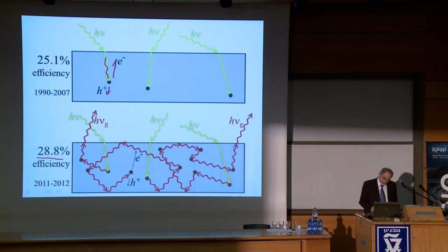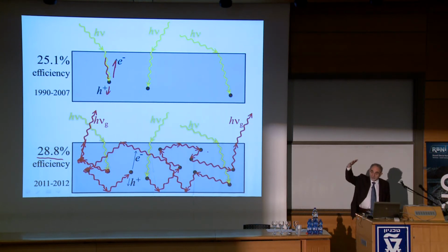In this new conception, the photons come in, they produce an electron-hole pair. The electron-hole pair recombines and gives an infrared photon. The infrared photon is reabsorbed, and sometimes it escapes. But most of the time, it is absorbed, it bounces around, is reabsorbed, bounces around, reabsorbed, and so forth. You end up with an infrared photon gas inside the solar cell. In fact, as you go to high performance, you could have only one sun coming in, but trapped internally inside the solar film, you could have 40 suns of infrared radiation bouncing around.